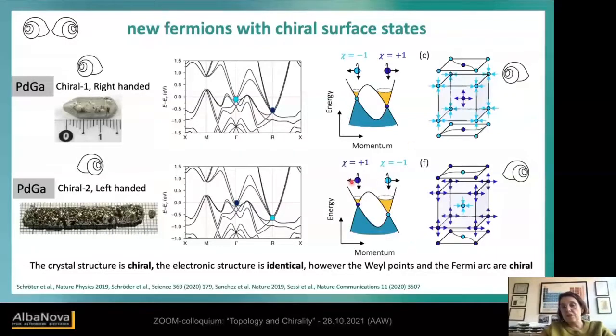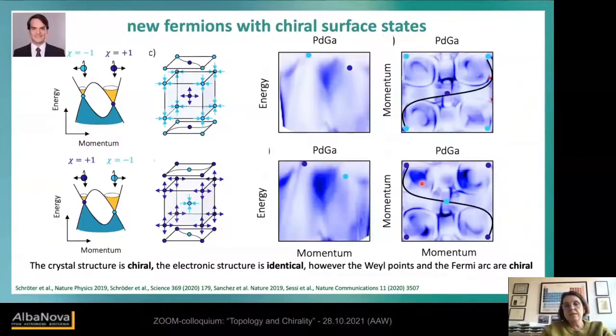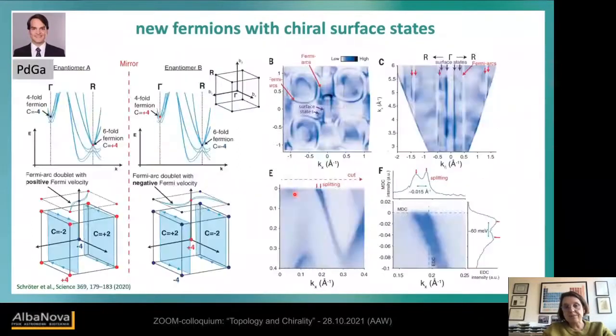So the electrons are also chiral here. This we see then. Sometimes you need a little bit of guidance for the eyes, but we have the chirality of the surface state in these two enantiomers, which you can nicely see. These are simply dots which get color, but we cannot really see it. But I will show you in a few slides that if we use circularly polarized light for the photoemission, we can see the chirality.